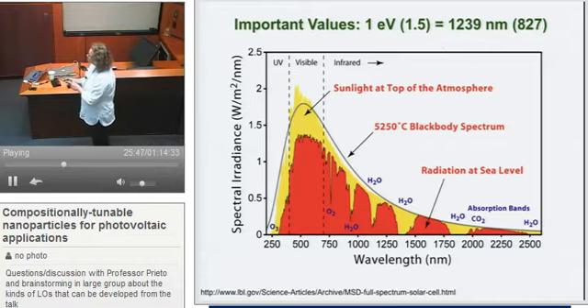So if you look here at spectral irradiance versus wavelength, the gray line is what you would calculate from the black body spectrum of the sun at 5250°C relatively. The yellow here is the sunlight that hits the top of the atmosphere. And then when you attenuate that with the molecules in our atmosphere that can absorb at the various wavelengths, so water, oxygen, CO2, what you get is the red. And this is the spectrum that hits the Earth. So a 1 eV band gap, you have absorption at about 1200 nanometers, 1.5 eV, that's about 827 nanometers.